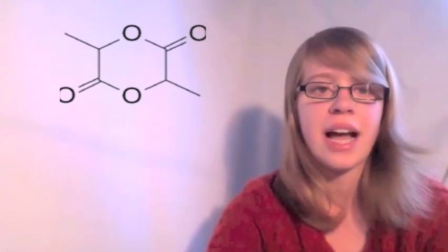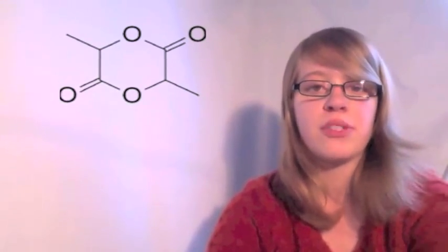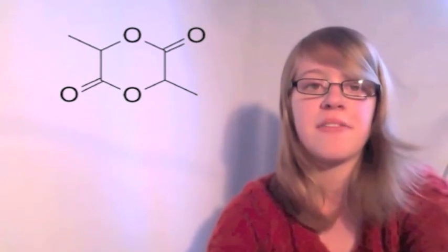So once the lactic acid is produced, we need to make the polymer PLA. We can't just use condensation polymerization of lactic acid because there is a competing depolymerization reaction which produces cyclic lactide. The equilibrium is reached before useful molecular weights of PLA have been formed. A solution to this problem is to isolate the lactide and polymerize it directly using a tin-2 ethyl hexanoate catalyst at 140 to 160 degrees centigrade.